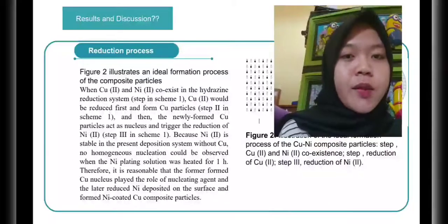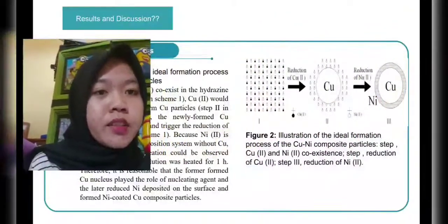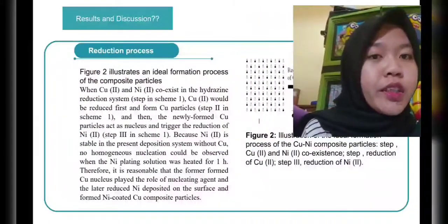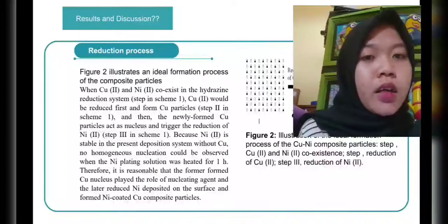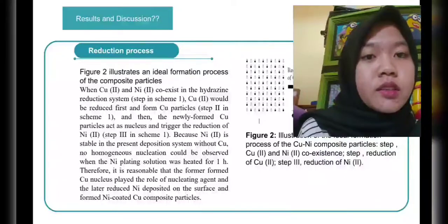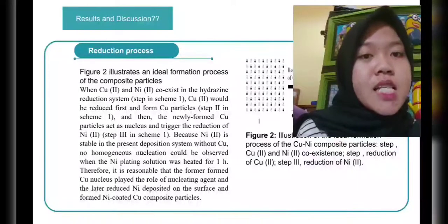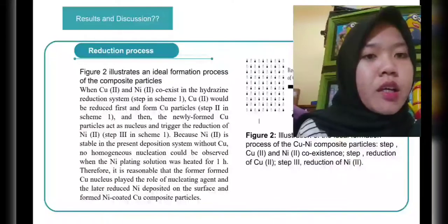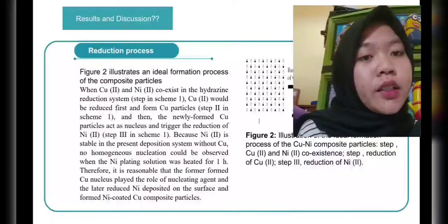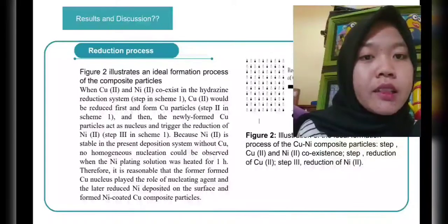First, reduction process. You can see figure 2 on my PPT. Figure 2 illustrates an ideal formation process of the composite particles when copper 2 and nickel 2 coexist in the hydrazine reduction system. Step 2 in scheme 1, copper 2 would be reduced first and form copper particles. Step 2 in scheme 1, and then the newly formed copper particles act as nuclei and trigger the reduction of